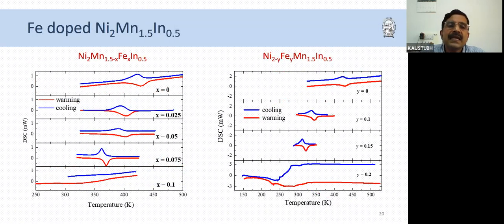So this is the differential scanning calorimetry study. You can see now we introduce Fe, and at around x equal to 0.1, the martensitic transition appears to have disappeared. At least in DSC, you don't see a very sharp transition, you see a very broad phase. In the other case also, you see a suppression of the martensitic transition and some very funny looking differential scanning calorimetry graph here. So in both cases, the martensitic transition has eventually disappeared.